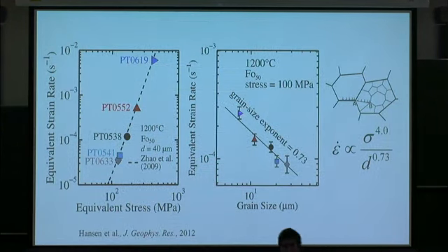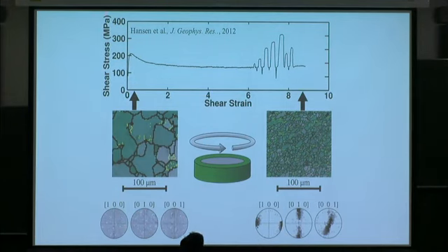And the point is, the reason to take it to really high strain is because the microstructure reaches this approximate steady state. The grain size has stopped evolving at this point. It's one of the big difficulties in this. You take something coarse-grained and you deform it just a little bit, you get a strain rate, but at the same time, there's a little bit of grain size reduction. And that potentially plays a role in the mechanical properties that you measure.